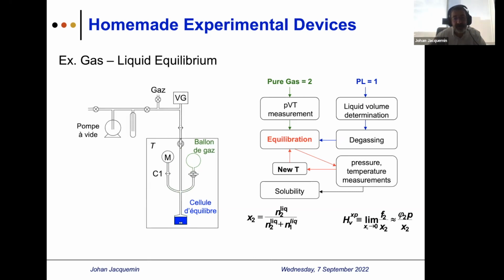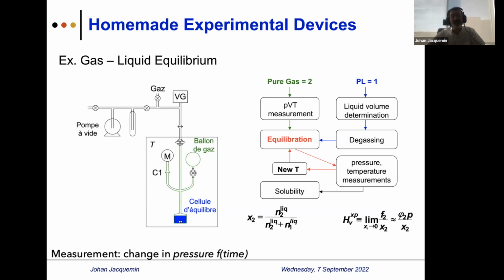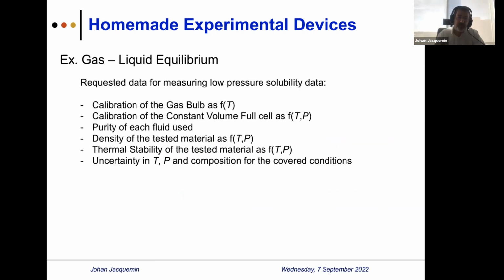Then you simply add your non-volatile liquid to the equilibrium cell. Then you can degas, if you must do it, you degas it, and then you just close the valve and put the trapped gas in contact with the liquid. By reaching the equilibrium time, which can take 1 week, 2 weeks, depending on the system, when the pressure is stable, depending on what sensitivity you have in your manometer, you can then determine the solubility. Of course, there is required data to measure low pressure solubility data by using such equipment.